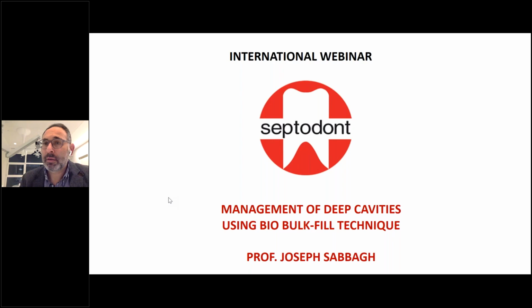If we leave it after 6 months, then it depends. Again, if you have a class one cavity, the results, of course, are better than if you have a class two cavity, because the class two cavity would tend to break a little bit and to be less resistant mechanically. But if you are working with a class one, then it will work. But I personally never leave it more than a couple of months in case the patient is struggling. But it's always necessary to replace it, because the wear resistance of Biodentine is not very strong over the long time, after 6 months, I mean.